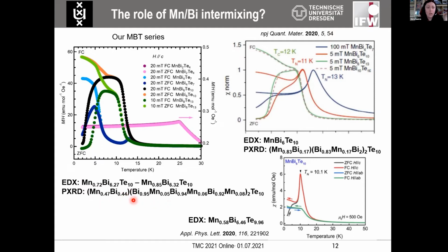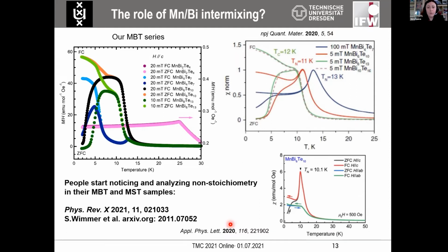that the results are also quite different with respect to the overall composition and the distribution of manganese between the voids. So we have consistently sub-stoichiometric samples, while other groups may get a little bit closer to one or even lower in the manganese content. So we are now looking a little bit more carefully into the manganese bismuth telluride family, trying to find out what are the connections between the population of the crystallographic sites and the magnetometry.